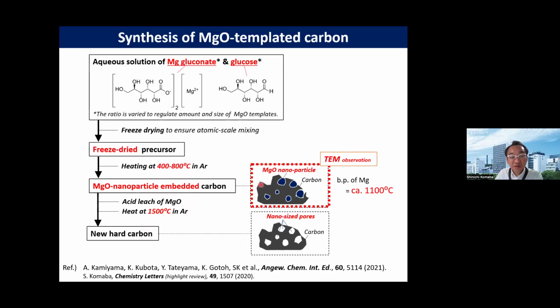during this heat treatment, magnesium oxide must be reduced first. Then MgO is converted to Mg metal. But the boiling point of magnesium metal is 1100 degrees Celsius, so the magnesium is easily evaporated and vaporized. Then after vaporization of magnesium metal, we have nano-sized pores in the hard carbon. So this means that magnesium oxide is acting as a template for nanopore formation.